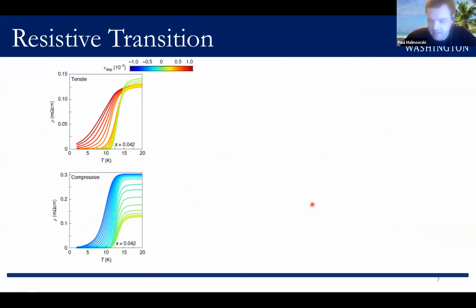So the first set of data I'd like to show you is the effect of strain on the resistive signature of the superconducting transition. So you're looking at the resistivity as a function of temperature of the underdoped sample for different amounts of both compressive and tensile strain given by the color bar. So the first thing to notice is that for small values of strain, which are these green curves, the resistivity above the transition changes by a large factor, while the transition temperature itself is relatively unaffected.